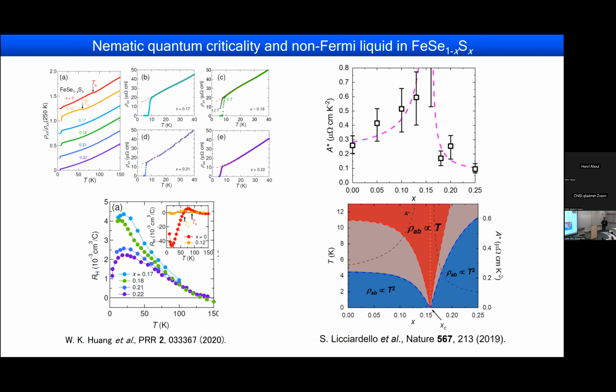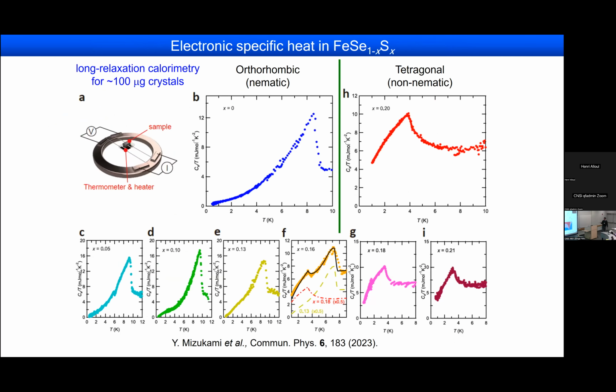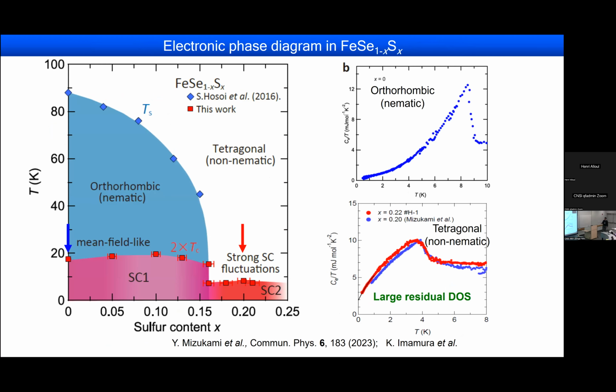Okay, but here today I would like to focus on the superconducting state. So we can measure the specific heat down to very low temperatures by using the so-called long relaxation calorimetry technique, which can measure the specific heat with very high precision for very small crystals. And from this kind of data, we can construct a thermodynamic phase diagram like this. So this is temperature, this is sulfur, and here is the nematic transition temperature, and this is Tc, actually 2 times Tc.